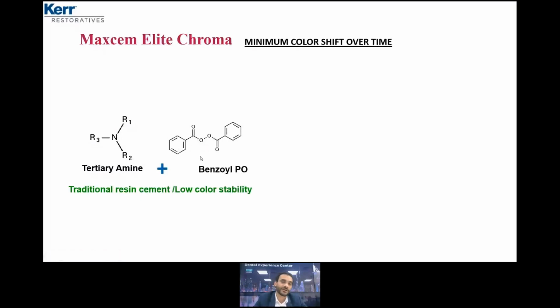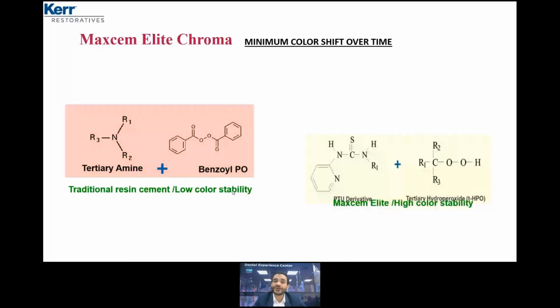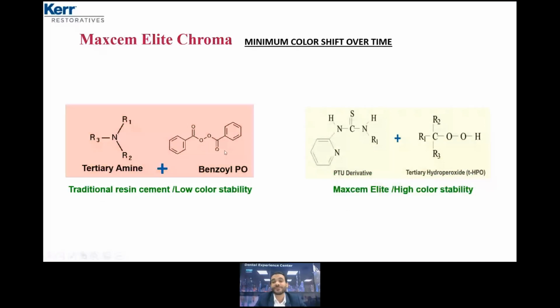They are super catalysts, with a high degree of polymerization and a proper polymerization process. But the main drawback of amine is low color stability, which means after some time the patient may complain about instability of the cement color. So what we did, we replaced the amine and benzoyl peroxide with a patented redox initiator. It's totally different. Same high degree of polymerization and proper polymerization process, but with high color stability, in order to avoid color shift over time.